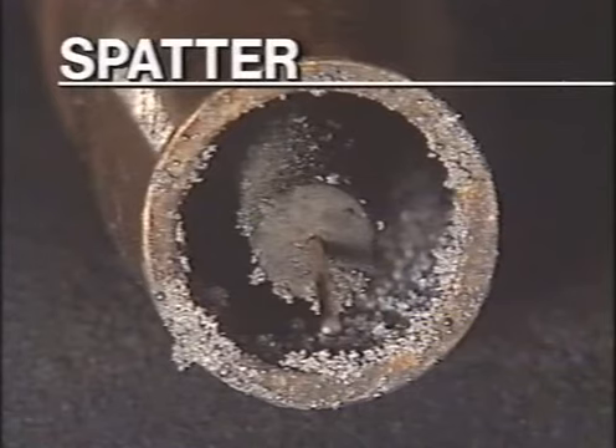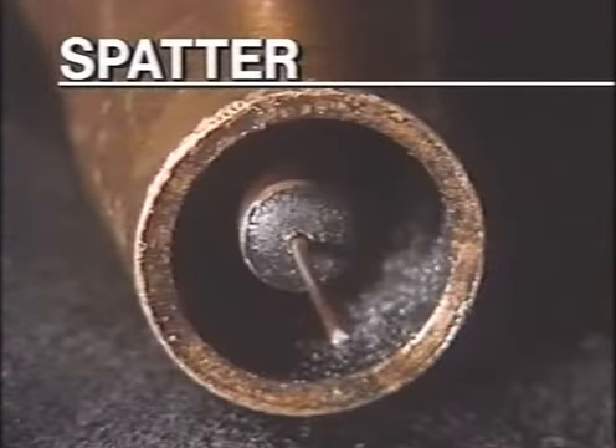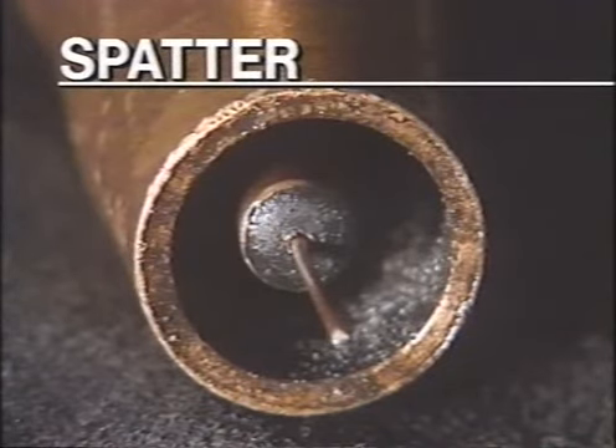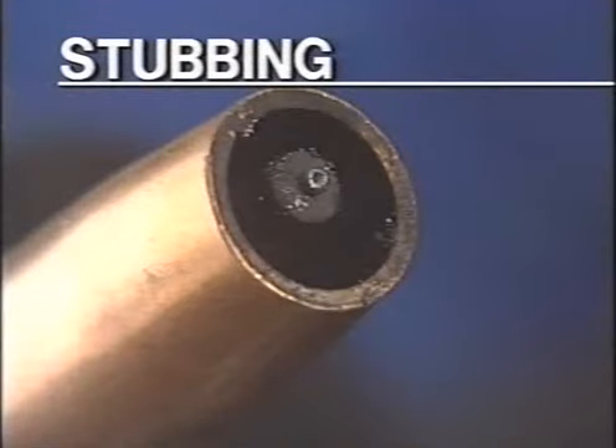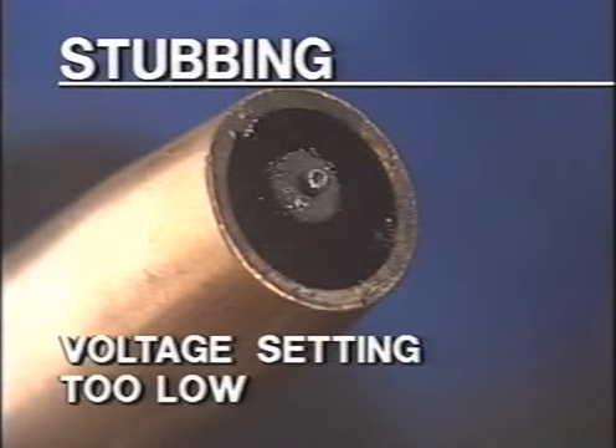It is important to be aware of the various weld faults and problems that can occur and how to overcome them. To eliminate the build-up of weld spatter which occurs on the inside of the gas nozzle, an anti-spatter spray can be used. This will ensure an even gas flow around the weld area. Stubbing occurs when the electrode wire sticks to the contact tip. This is caused by selecting a voltage setting which is too low.